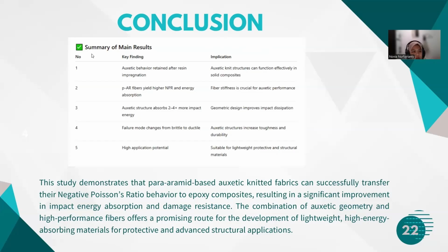Conclusion. Summary of main result. Auxetic behavior retained after resin infusion. Para-aramid fiber yields higher NPR and energy absorption. Auxetic structure absorbs far more impact energy and changes from brittle to ductile, and has high application potential.